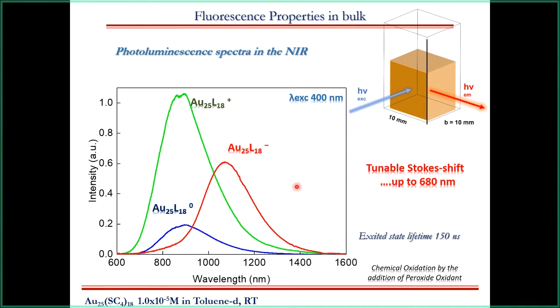We also proved that it is possible to play with the charge to tune the emission properties of the cluster, and also that we have an atomically precise structure with a very high Stokes shift, because we can excite this system at around 400 nanometers and have an emission in the strong near infrared region, which could be very useful if you think about bio-imaging applications.